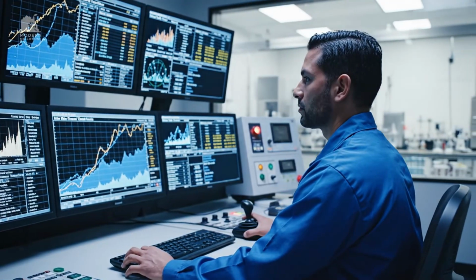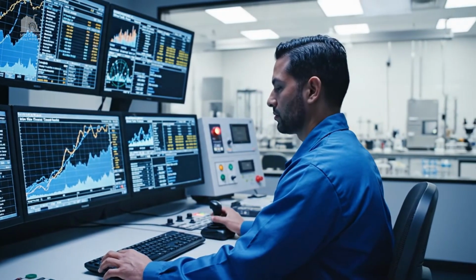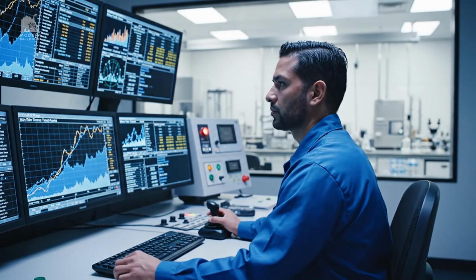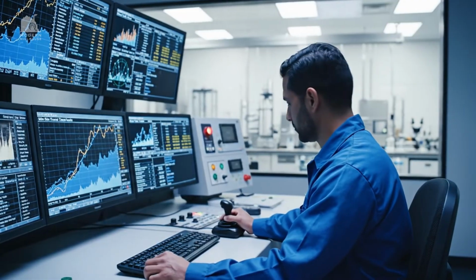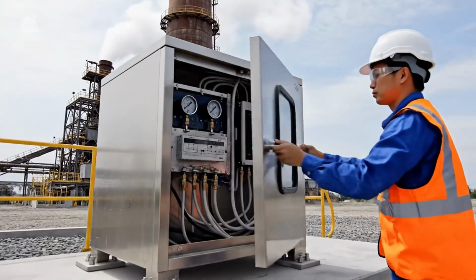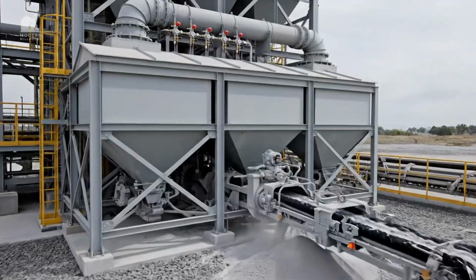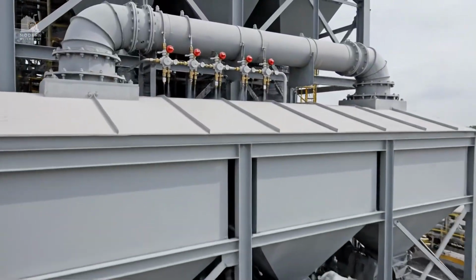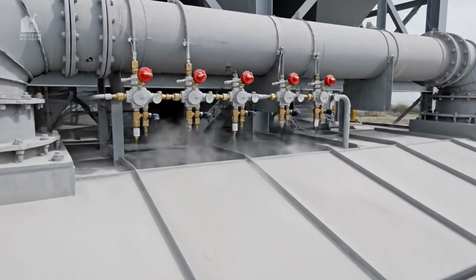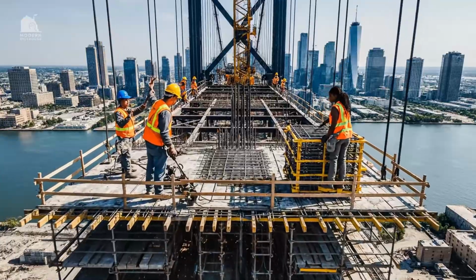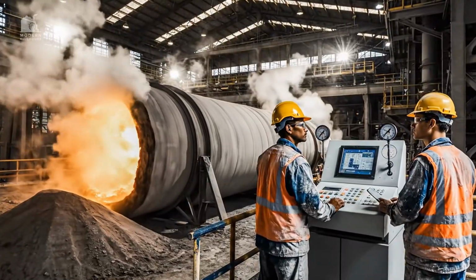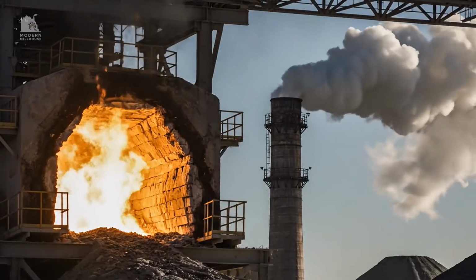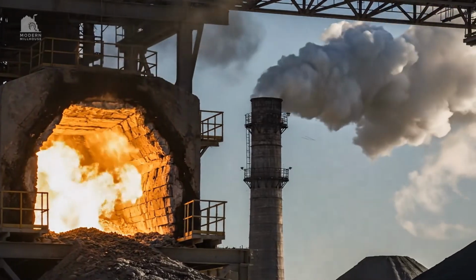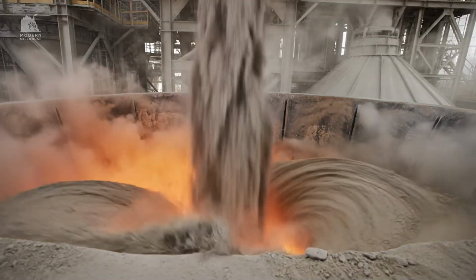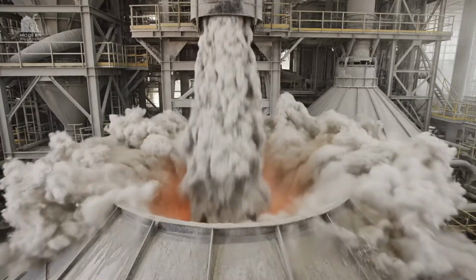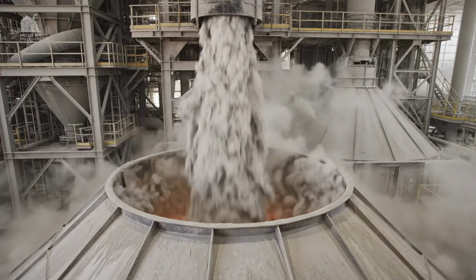Plants measure oxygen, carbon monoxide, and dust, and they calculate CO₂ using fuel data and process models. Continuous monitoring ensures environmental compliance, while filters keep particulate emissions low despite high material throughput. Globally, cement is responsible for a significant share of CO₂, often cited at roughly 7% of total emissions. Chemistry emissions occur mainly during calcination, before the material even reaches the hottest burning zone.